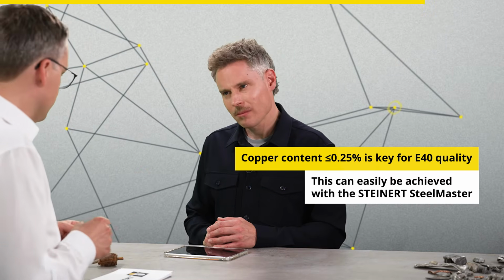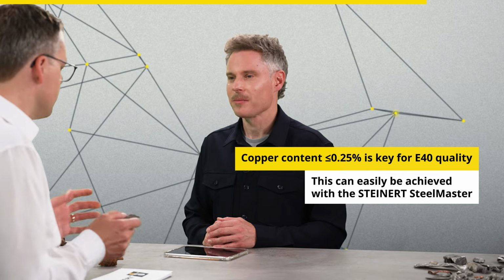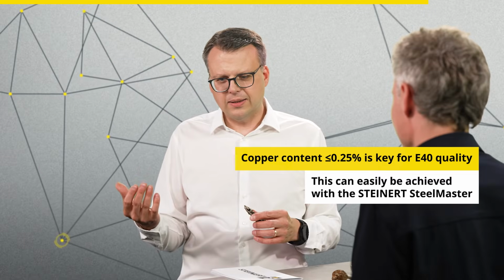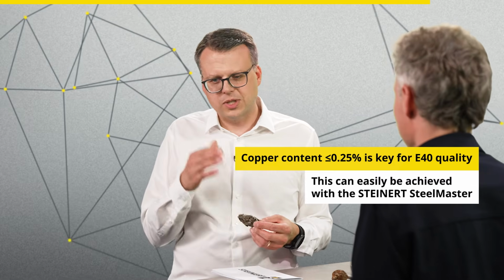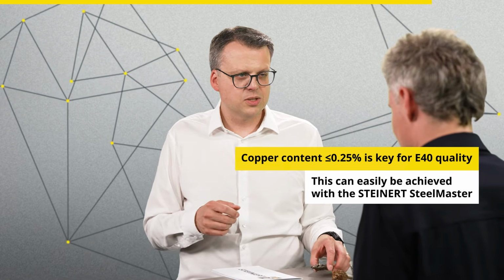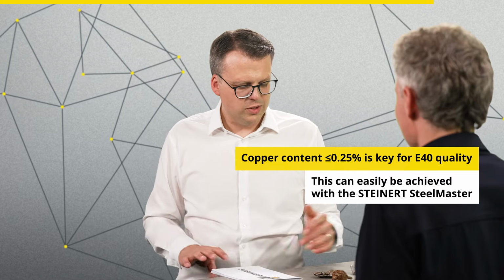So a standard requirement with regards to the E40 grade is to have a copper percentage of a maximum of 0.25%. Some customers even require 0.2%, which is also commonly used. And this is something we can achieve by just using the SteelMaster without any additional hand sorting to achieve the E40 quality standards here. So the SteelMaster from STEINERT is therefore a robust technology for complying with today's limit values, as you mentioned.